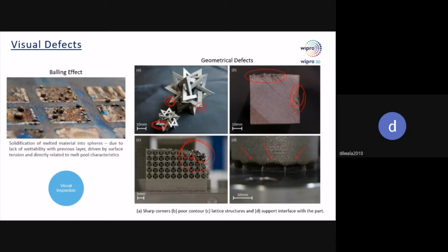For these sorts of things, we always prefer a soft recoater. If you don't use a soft recoater and use a hard recoater, these sorts of issues can happen. Then support interface. Here the support is coming and matching with the actual part. See, it is matching with the actual part. This will be difficult to cover afterwards. These are the different visual defects that can arise on the component.